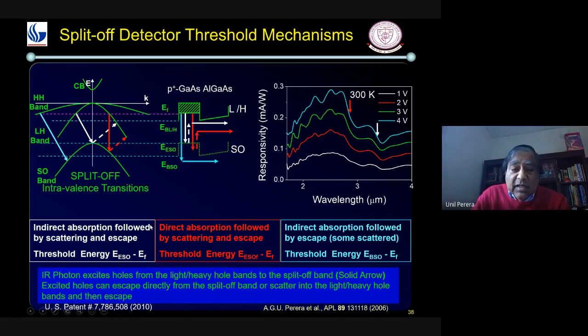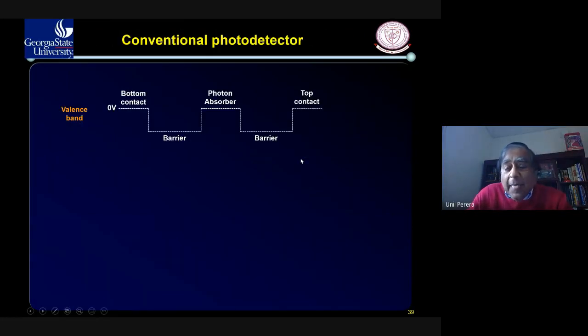And this is, we came up with the structure to detect in this 3 to 5 micron range here, room temperature detector. So this is an unexpected result. We got funding and we got a patent for this also to develop a room temperature 3 to 5 detector. Then we were trying to improve the performance of this detector.